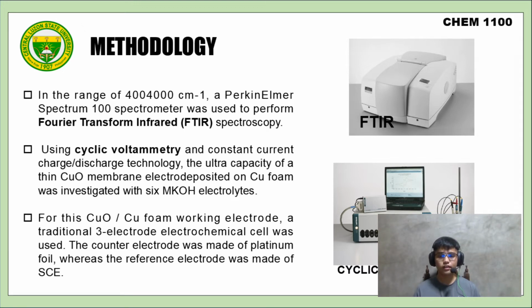For this copper oxide copper foam working electrode, a traditional 3-electrode electrochemical cell was used. The counter electrode was made of platinum foil, whereas the reference electrode was an SCE.